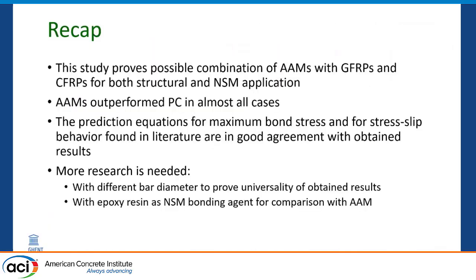So in the recap, this study proves a possible combination of alkali-activated mortars and FRPs for both structural and near surface mounted applications. The AAMs outperformed conventional concrete in almost all cases. The prediction equations for maximum bond stress and for stress-slip behavior found in literature are in good agreement with obtained results, and more research is needed with different bar diameter and with epoxy resin as NSM bonding agent for comparison with AAM.